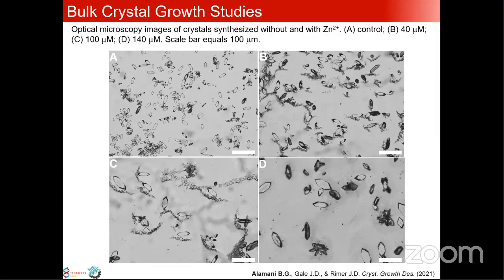So here I'm going to present to you some of the results that we've gathered. We did this in vitro, in a test tube, using a biomimic solution that mimics the average ionic strength of urinary systems. The first panel is a microscope image of a typical calcium oxalate crystal. Then we progressively added zinc: 40 micromolar, then 100 micromolar, and then 140 micromolar.